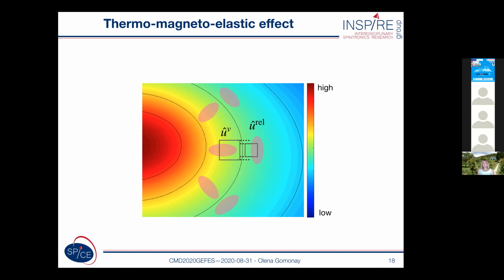In other words, this inhomogeneous volume effect induces strain incompatibility of the layer. And this incompatibility can be removed by additional strains. And these additional strains, relative strains, as they are denoted here in this slide, are shear strains. So they are anisotropic, as shown by ellipses. And what is also important, the orientation of this strain is different on the other sides of the interface region. So the ellipses at the hot corner are horizontal, and in the cold corner are vertical.